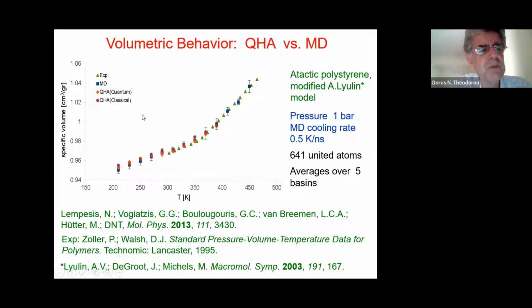You see 2 sets of results. One is quantum mechanically calculated, the quantum mechanical vibrational partition function. The other one is classical. They are very close to each other because the temperatures are rather high here. And they lead smoothly into the melt behavior. The blue points here are melt predictions for the volumetric properties of the polymer. So there is a clear break in the slope of the specific volume versus temperature, which is a characteristic of the glass. The glass temperature is around 100 degrees centigrade, or 373 for real polystyrene. And it so happens that these data points are not very far from that. So we see that this quasi-harmonic approximation gives us a measure of the expansivity of the glass that is not too bad when compared with experiment.